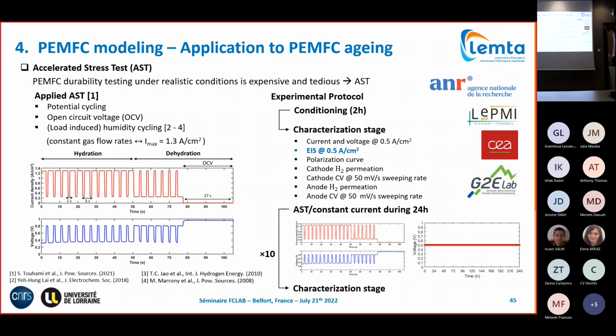And actually, here's just an outcome we also had, because it was done in the framework of an ANR project in which we analyzed the propagation of defaults as well. So the impact of a default in your MEA on the aging. We analyzed MEAs with a default, a leakage of active layer, how this impacts the aging, as well as the propagation. And we observed some propagation of our defaults along the cell. We can have a more detailed discussion on this afterwards.